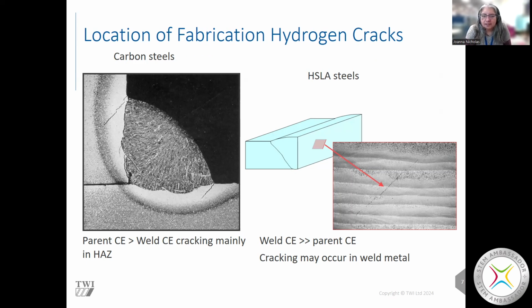So if the carbon equivalent of the parent material is higher than that of the weld metal, we tend to get cracking in the heat affected zone. If the carbon equivalent is less in the parent material than in the weld metal, then the cracking tends to be in the weld metal. So those are the locations where fabrication hydrogen cracking occurs.